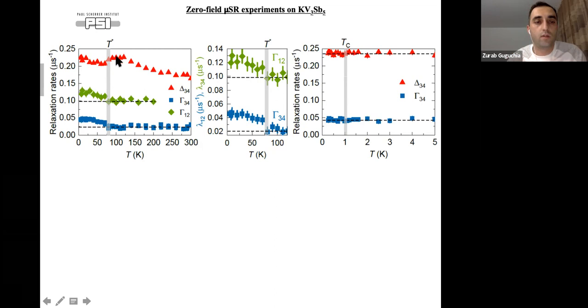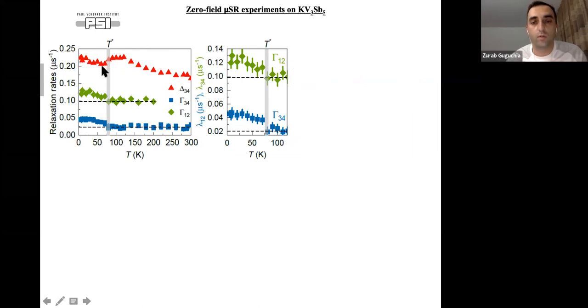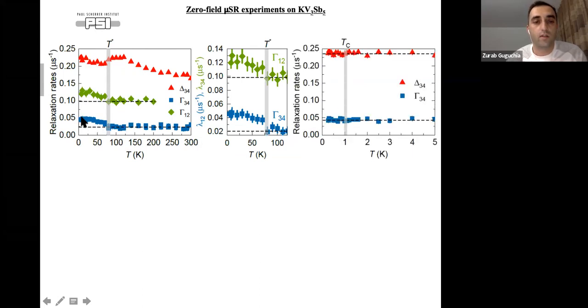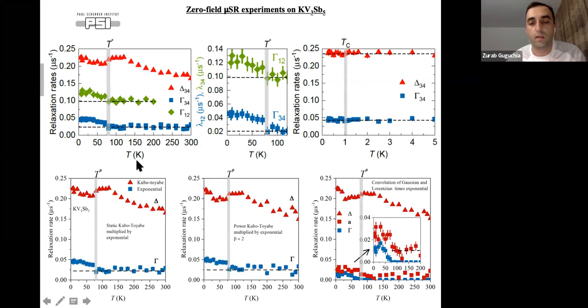This increase is also accompanied by a non-monotonous behavior of the nuclear relaxation rate, with a maximum here, then some kind of shallow minimum, and then it increases again. So we have this non-monotonous behavior, which is reproducible also in the rubidium sample and different samples of potassium. But we clearly have this increase of the exponential relaxation rate. We don't want to go into details, but if you try different models, you always have the increase of the relaxation rate just below the charge density wave transition temperature.